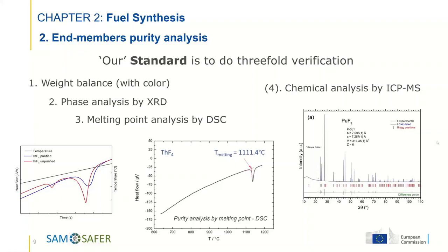For impurities, we found no impurities in principle. But as many of you or all of you know, XRD is also not the most sensitive method. But it's relatively straightforward to do, so we always do the XRD. If XRD shows impurities, we know that we have to refluorinate or rechlorinate. If it shows no impurities, it still doesn't mean it's 100% pure, but it means we can proceed to the